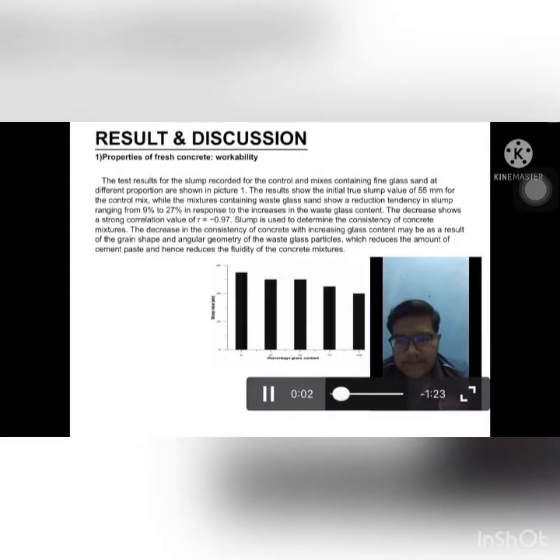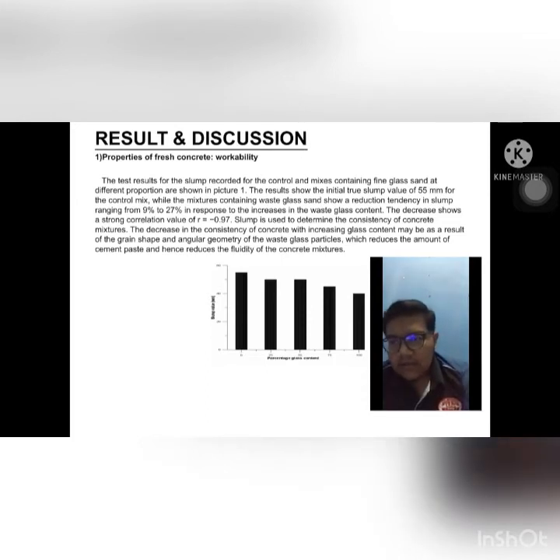Results and discussion. 1. Properties of fresh concrete. Workability. The test results for the slump recorded for the control and mix containing fine glass sand at the different proportions are shown in Picture 1. The results show an initial true slump value of 55 mm for the control mix, while the mixtures containing glass sand show a reduction tendency in slump, ranging from 9% to 27% in response to the increase in the waste glass content. The decrease shows a strong correlation value of R equal to negative 0.97.